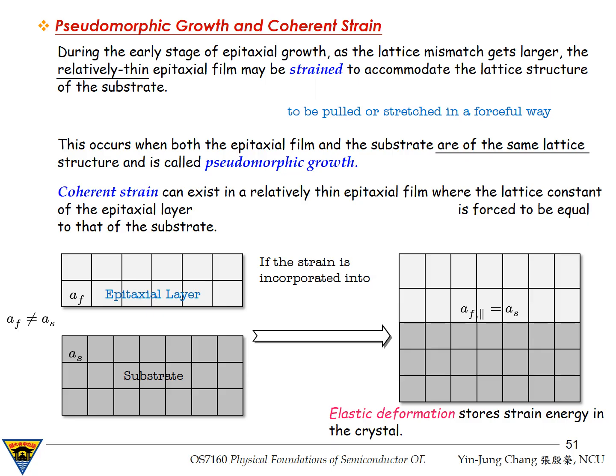The term pseudomorphic literally means false shape. The film adopts the lattice shape of the substrate, even though its own natural lattice constant is different. So let's take a look at the diagram shown on the page. The substrate has lattice constant A sub s, while the natural lattice constant of the epitaxial film is A sub f. During pseudomorphic growth, the lattice spacing parallel to the interface is forced to match that of the substrate. That means the in-plane lattice constant of the film effectively becomes that of the substrate. So we have A sub f parallel equals A sub s.